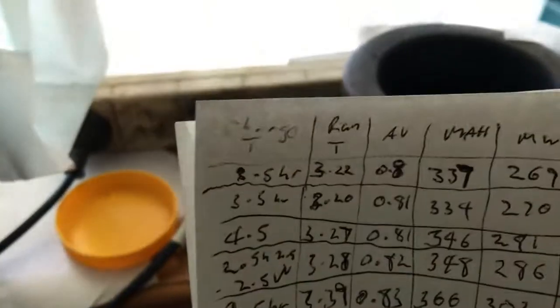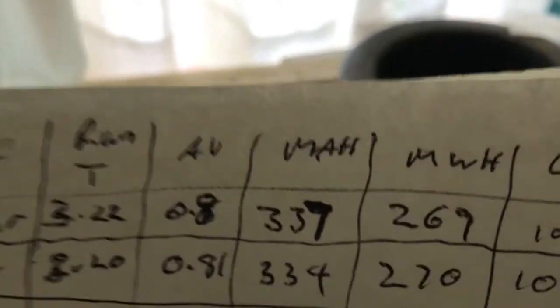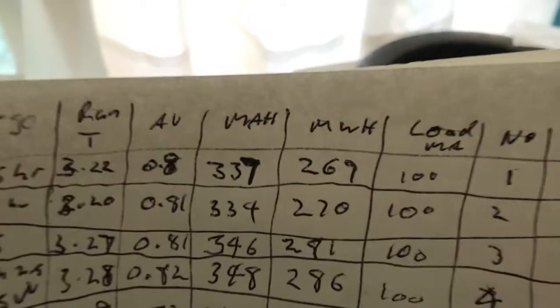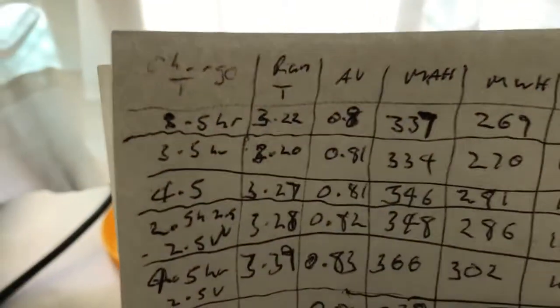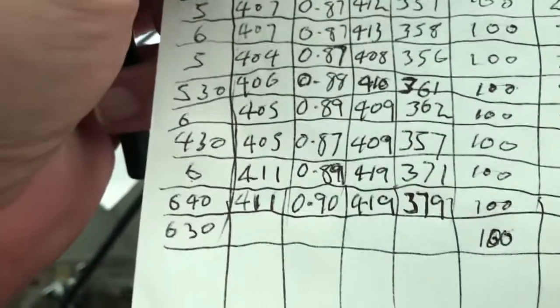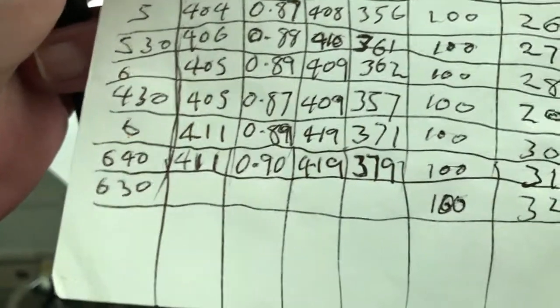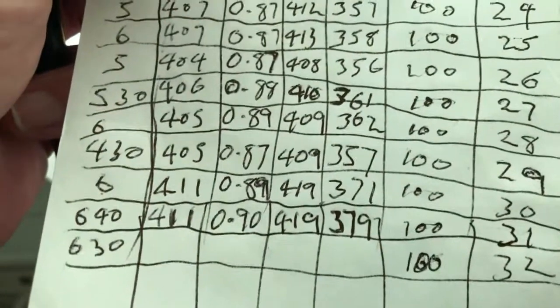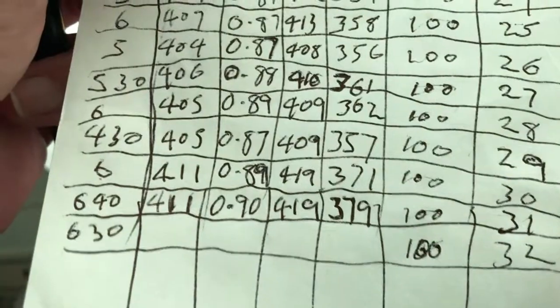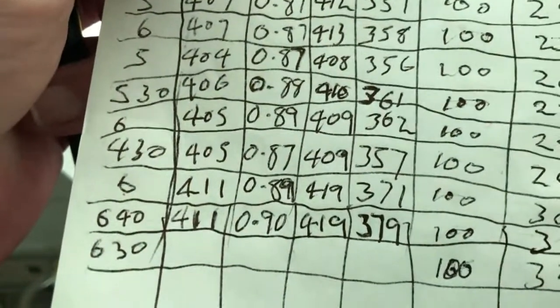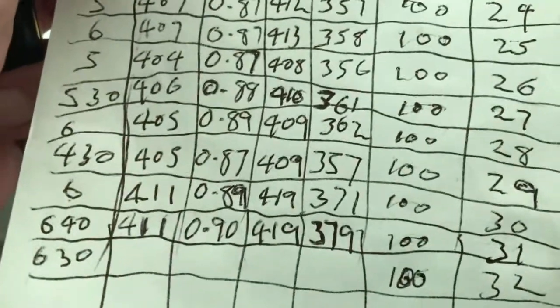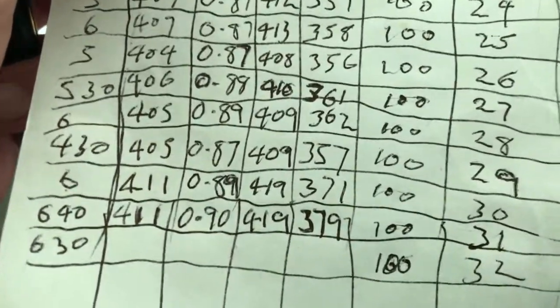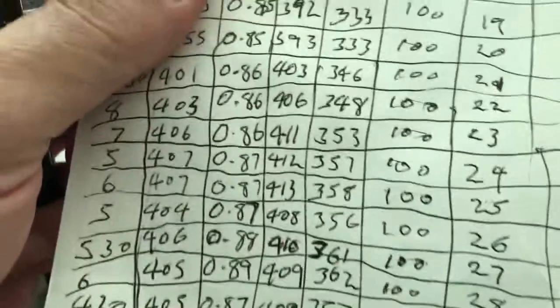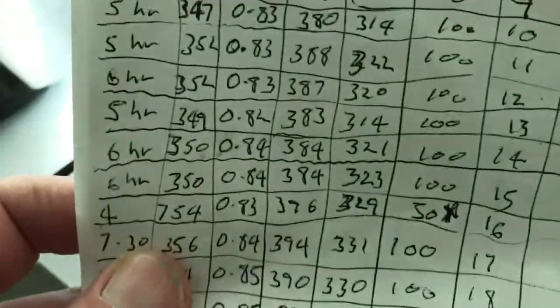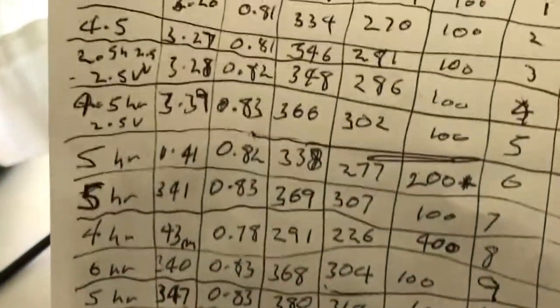And there's the little chart. Milliamp column is there. Milliwatt hours is there. It's around about, this charge was 6 hours and 30 minutes. The charge before it was 640, and we got 4 hours and 11 minute run time. The average voltage is going up, that's at 0.9. If you look at that column, it's pretty stable.